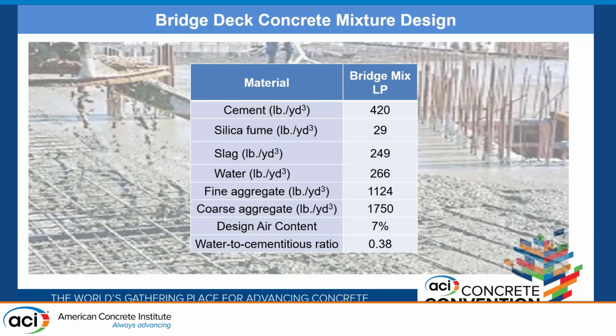So anyway, this is the concrete. I felt pretty bad when I saw that, Mike, the cement contents. This analysis was done a little before that. Usually we have it much lower than this now to get the paste fraction down, or they have to use an SRA or something to take account of that. Usually it'll be less, but this is an example. So whatever mix you want to put in there, you can do it, and it'll just change the curves a little bit, and you work accordingly. So that's the mix we used.